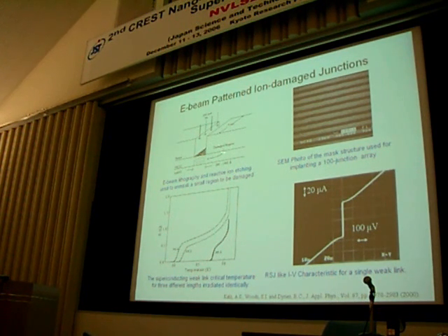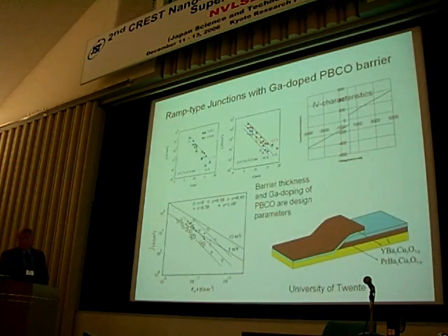And that means you very critically depend on the lithography and on the quality of the electron beam lithography. This roughness determines very strongly already the current which can be transported through such a structure. The IV characteristics look very nice, just like you would wish all the IV characteristics would be for HTC junctions.